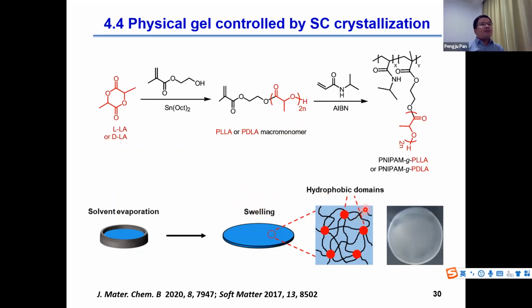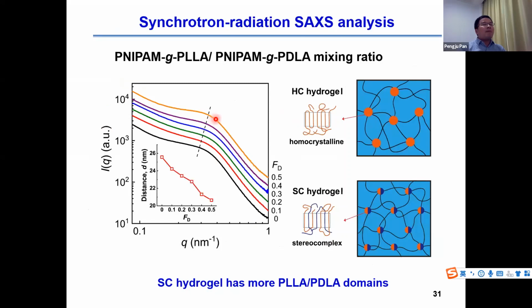In this hydrogel, hydrophobic PLA and PDLA act as the physical cross-linking domains, which are surrounded by the hydrophilic poly(N-isopropylacrylamide) chains. We analyzed the network structure by SAXS, where we can see a broad correlation peak in the profile. We can estimate the domain size by fitting this peak.